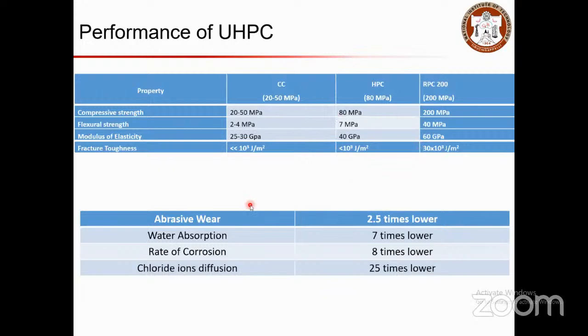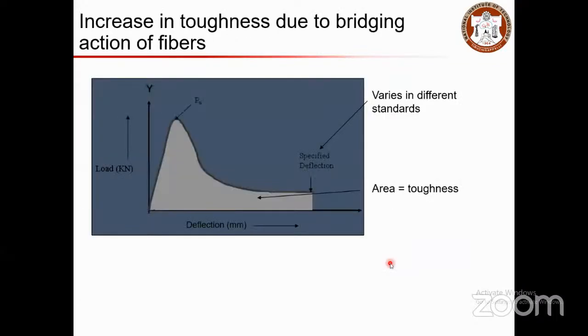So these structures will be very helpful when you need to have abrasive wear resistance in structures, and in such scenarios the water absorption will be 7 times slower, and rate of corrosion will be 8 times slower, and chloride ion diffusion will also be lesser. So the fibers are basically helping to enhance the performance. So this is what is expressed here. The concrete has a major role, and then the fibers will start bridging the cracks, and that increases the toughness in your material.